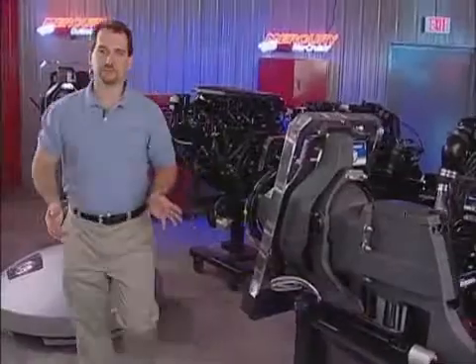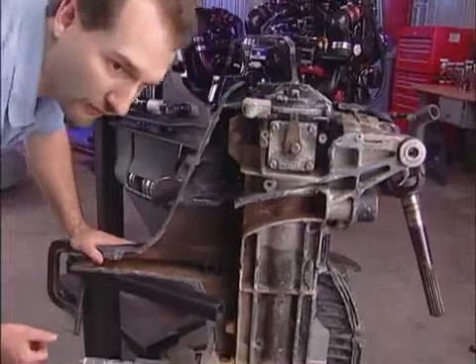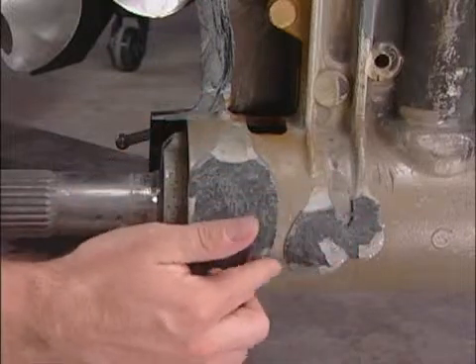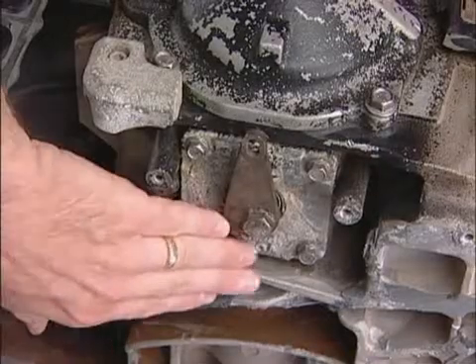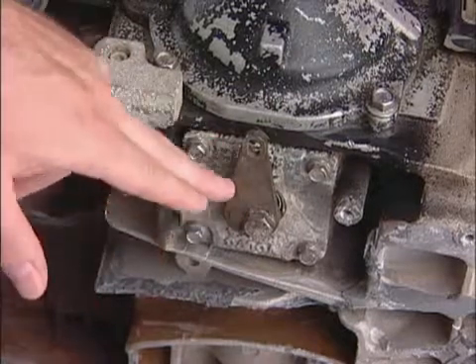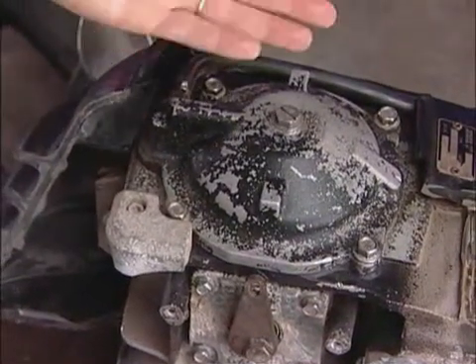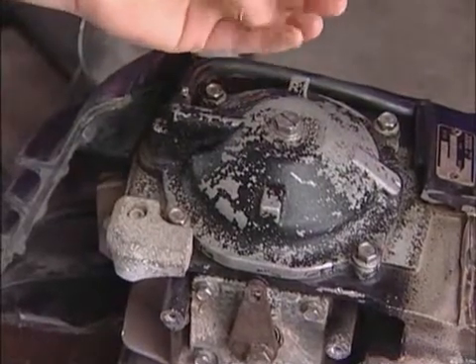For a comparison, let's take a look and see how the MerCruiser SeaCore system with closed cooling on its engine compares to the Volvo Ocean Series drive. Many people are surprised to find out that this is an aluminum drive just with some glued-on cladding. As you look at the top portion of the Volvo Ocean Series drive, you can see some evidence of corrosion in the aluminum and with the shift lever. You can also see some pitting on the anode showing that there's active electrolysis going on. And as far as the paint performance on the top cap — so much for the composite drive.